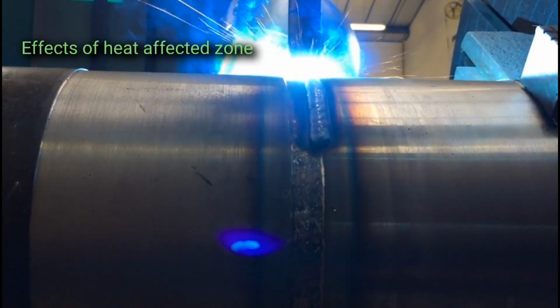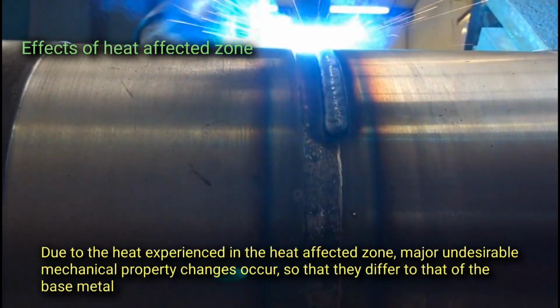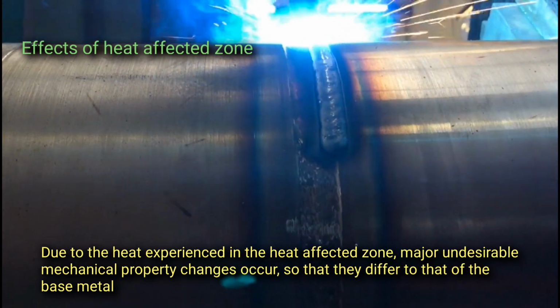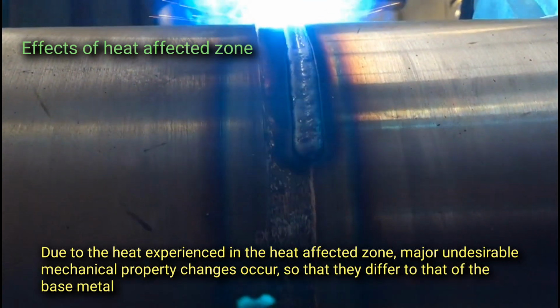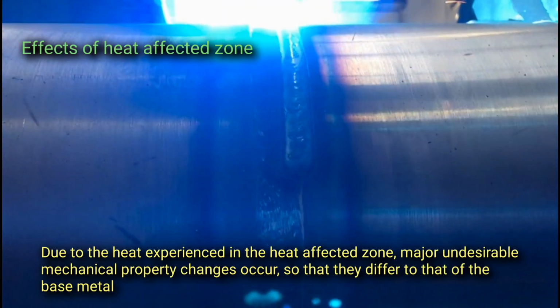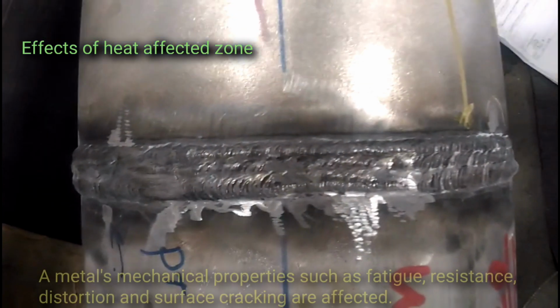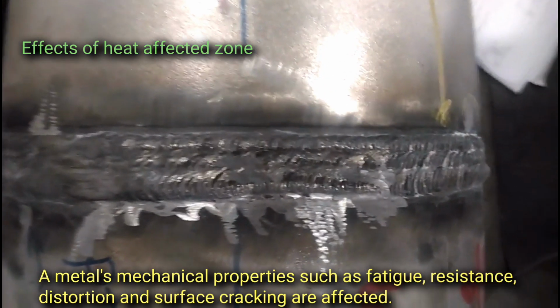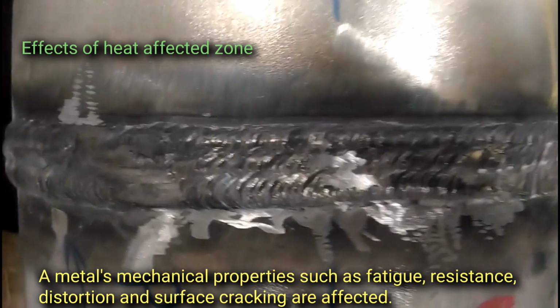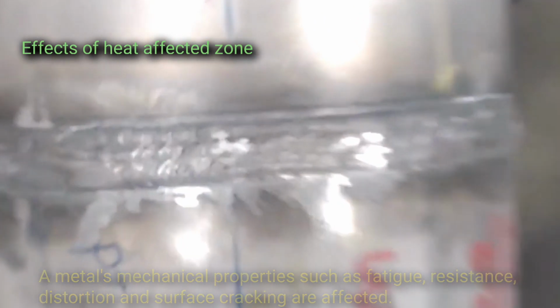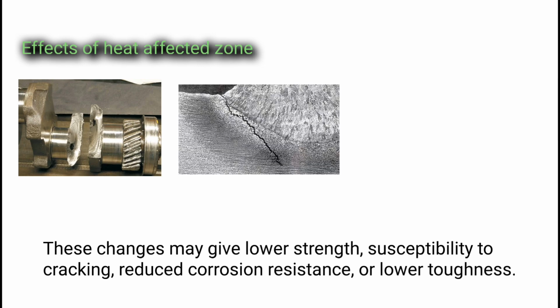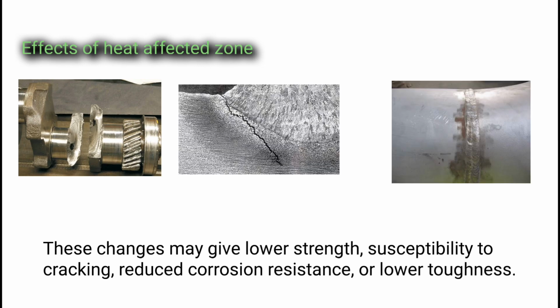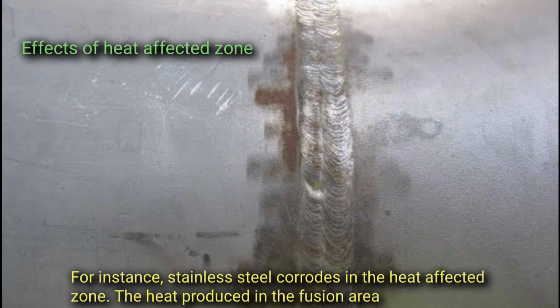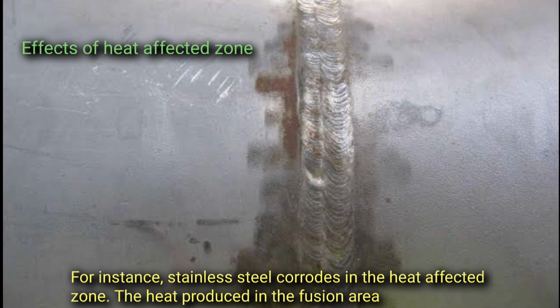Effects of the heat-affected zone. Due to the heat experienced in the heat-affected zone, major undesirable mechanical property changes occur, so that they differ from those of the base metal. A metal's mechanical properties such as fatigue resistance, distortion, and surface cracking are affected. These changes may give lower strength, susceptibility to cracking, reduced corrosion resistance, or lower toughness. For instance, stainless steel corrodes in the heat-affected zone.